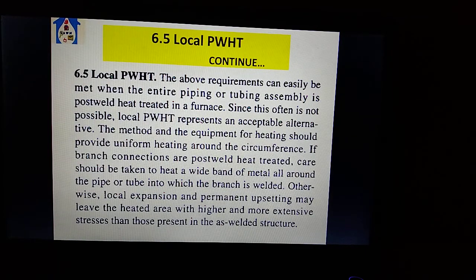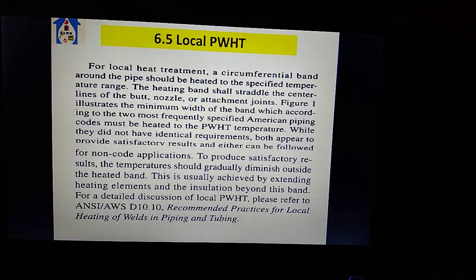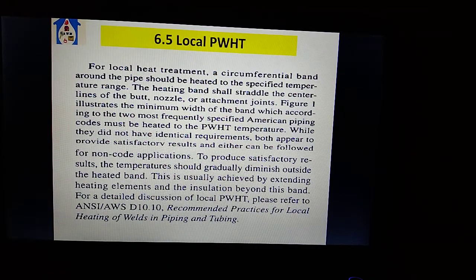Otherwise, local expansion and permanent upsetting may leave the heated area with higher and more extensive stress than those present in the as-welded structure. For local heat treatment, a circumferential band around the pipe should be heated to the specified temperature range. The heating band shall straddle the center line of the butt, nozzle or attachment joint.